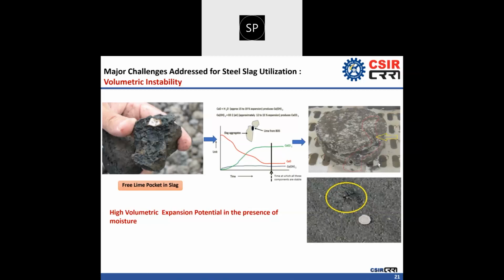If this treatment is not done, then this sort of failure in the bituminous mix can happen. This is a Marshall specimen which we cast in our lab with the untreated BOF steel slag sample, and when we put it into the water bath at 60 degrees centigrade, within an hour itself, due to the presence of high free lime, these cracks developed, and the mix crumbled when we removed it from the water bath.